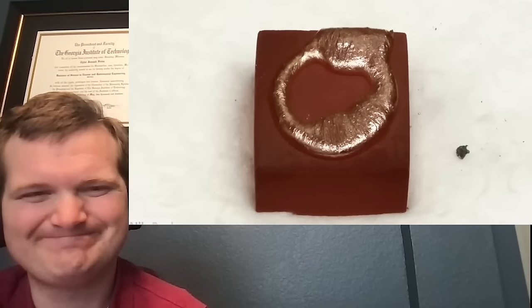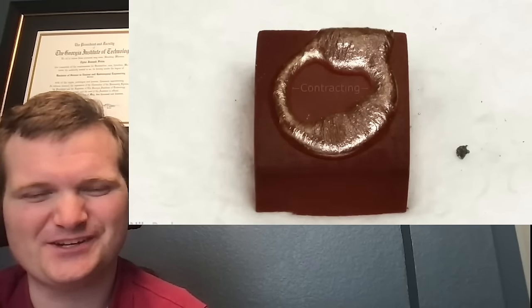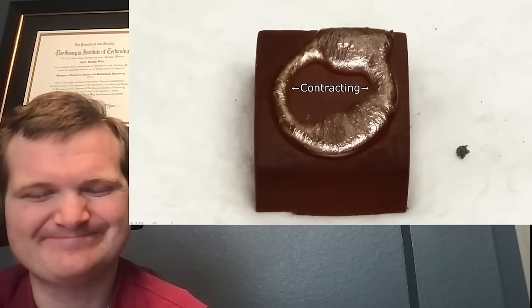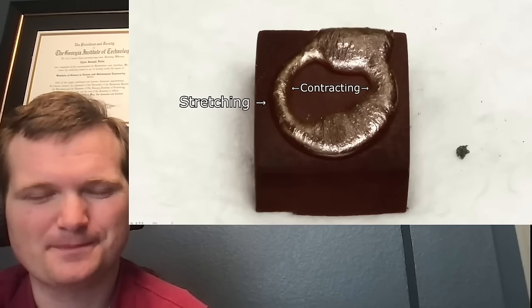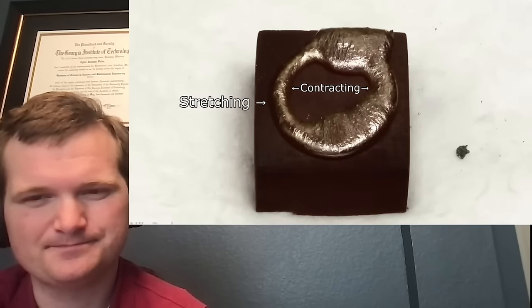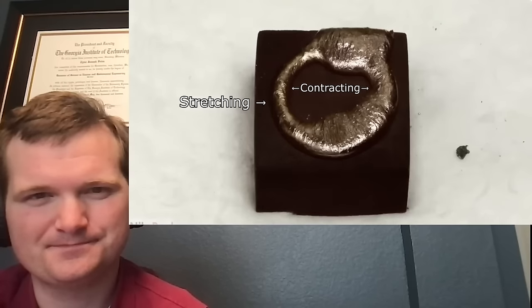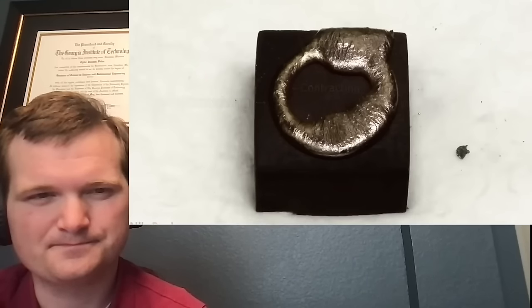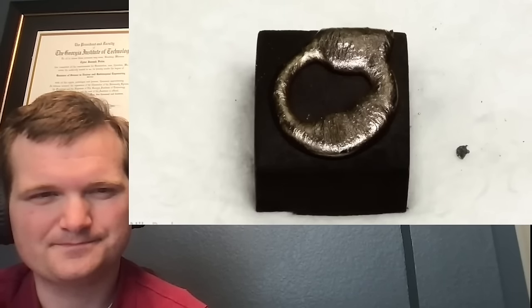This was also a huge issue because this meant that the inner side of the ring would start contracting while the outer side of it would stretch. And since the purple gold had no real malleability or ductility, this would almost definitely cause it to break. To try and avoid this, I'd purposely angled the inner edges of the mold, hoping that as it contracted, it might pop itself out without cracking.